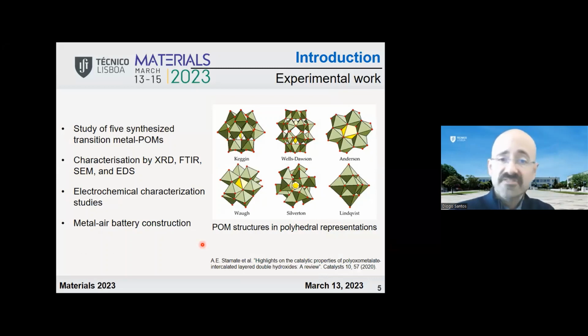We synthesized 5 different metal polyoxometalates. We did the characterization of those materials by XRD, Fourier transform infrared spectroscopy, SEM, EDS, and then we did the electrochemical characterization, because we are an electrochemistry group, collaborating with other material science groups that also work on the synthesis, which was mostly done in Belgrade, and here in Lisbon we did the electrochemical characterization. We also constructed a small lab metal air battery that could test the developed materials.